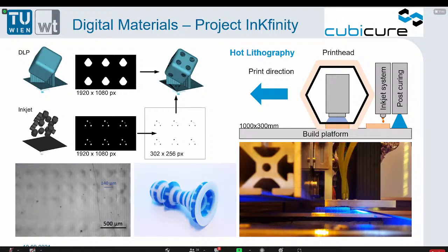Well, one of the drawbacks from the SLA side was that you cannot really do multi-material printing. On the other hand, inkjet can do this, but inkjet has its limits because usually the parts are very brittle because the resins have very low viscosity. By combining those two, we can produce structures which have a good resolution and good surface quality from the SLA, but also with the SLA part, we can print very high viscous materials. So hopefully more tough materials.